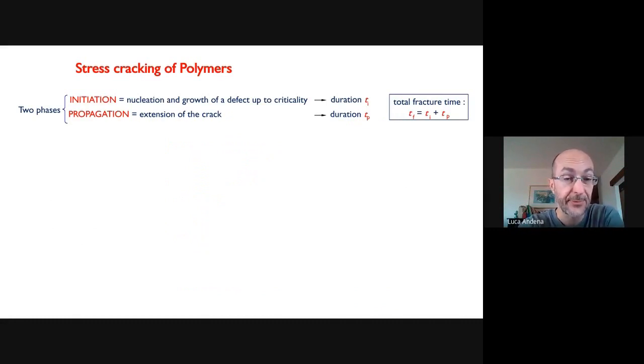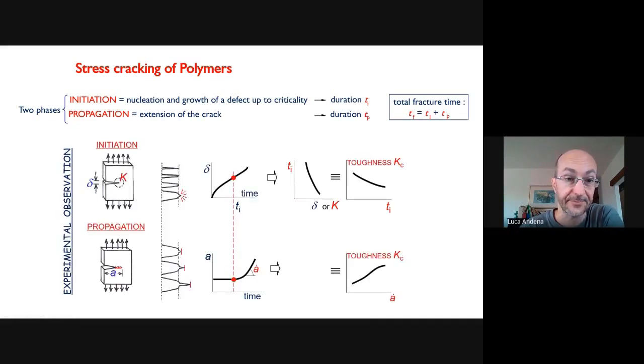is one of those. And the approach is identical to the approach which is taken to consider stress cracking of polymers in general. In polymers, which are viscoelastic materials, you assume there are two phases: initiation, which is the time required for the defect to become critical, and propagation, which is the time required for said defect to grow through the thickness of the product and cause failure.